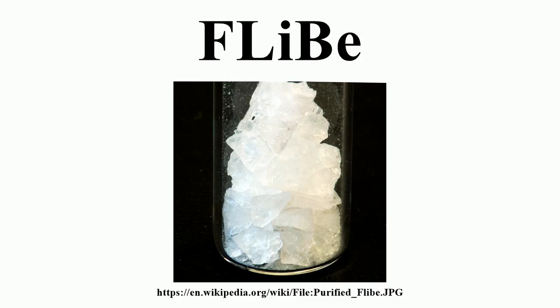The redox potential is an innate and measurable voltage in the salt which is the prime indicator of the corrosion potential in salt. Usually, the reaction is set at 0 volts. This reaction proves convenient in a laboratory setting and can be used to set the salt to 0 through bubbling a 1-to-1 mixture of hydrogen fluoride and hydrogen through the salt. Occasionally the reaction is used as a reference.